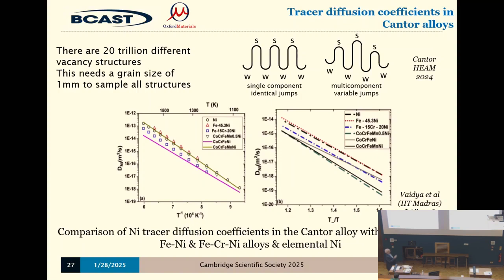But in one of these multi-component materials, the jumps are all different. And what happens is it slows down the overall rate at which atom motion happens, because they get stuck in low energy positions and they start going round and round in circles and things like that. That's very, very important. Because of these local strains, they get stuck, and that means that they're very resistant to degradation. They're very good at radiation resistance. They don't degrade under radiation anywhere near as much as other materials. They're very good at high temperatures. They don't degrade so easily when exposed to high temperatures. They're very good against corrosion. So they're resistant to all these things, mainly because of these local structures.